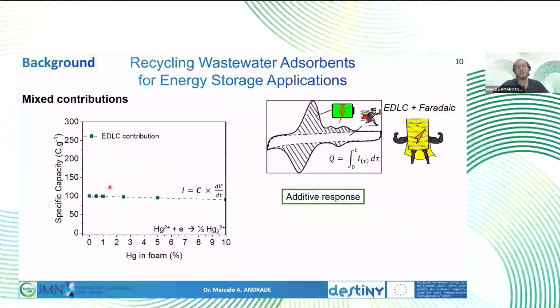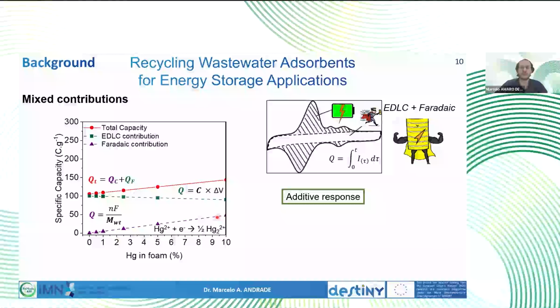So this is just to exemplify, once you have a powder that is loaded with a certain quantity of heavy metal. The more heavy metal you have, the lower the percentage mass of carbon powder naturally. So that would be the contribution from the double layer capacitance, just because you're decreasing its mass. And that would be the contribution of the metal. So the more metal you have, the higher the energy it could contribute to your system. And overall, the total capacity is expected to be just the sum of both.